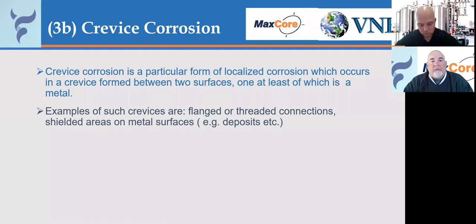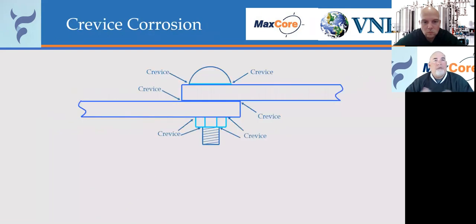Now, when we're talking about crevice corrosion, this is where you have two areas put together that form a crevice between two different surfaces. This can be something as simple as flanged or threaded connections, or pieces of material bolted together. This shows you all the different crevices created just by bolting two materials together. You have crevices where the bolt head is, crevices where the plates come together, and crevices all over. So you can see where you might have an attack in that location if product gets underneath here.